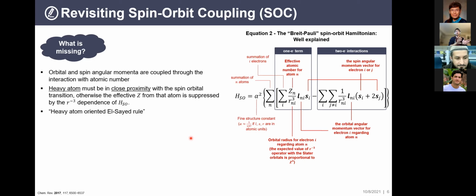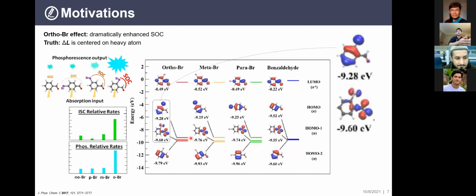so that we can use a heavy atom to directly induce the orbital angular momentum change. And we first thought of this heavy atom oriented El-Sayed rule, or more precisely heavy atom oriented orbital angular momentum manipulation. We actually almost discovered this years ago when we studied bromine's position relative to the carbonyl group, which can induce orbital angular momentum, and how this position change will lead to different intersystem crossing of phosphorescence.